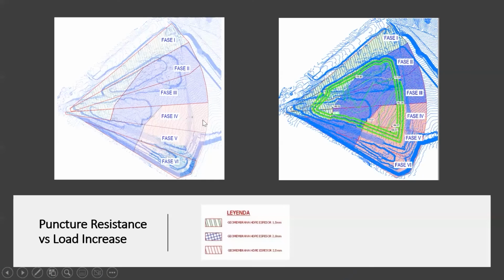So to do that, we took the most recent topography and revealed it with very old information, which was the original configuration for different phases here. We are talking about 6 phases here only, and with different thicknesses in this case of geomembrane that was built. In this case, between 1.5 millimeters, 2 millimeters, and 2.5 millimeters in these areas.